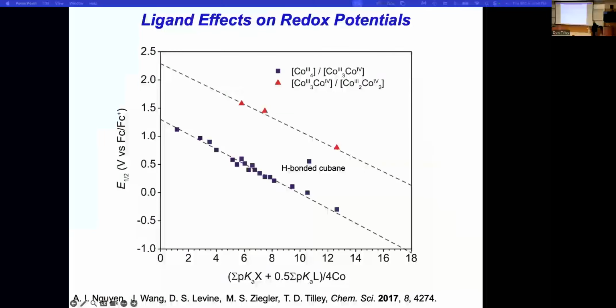So the next interesting observation is that those redox potentials obey a linear correspondence to a simple parameter, which is the summation of the pKa's of all eight ligands on the cubane. A little bit surprising, but it works pretty well. And so this linear free energy relationship is very useful for evaluating intermediates in the mechanism, for catalyst design, and for learning more about the cubanes. So this first line is that first oxidation. The second line is the second oxidation. I only have three of those there.